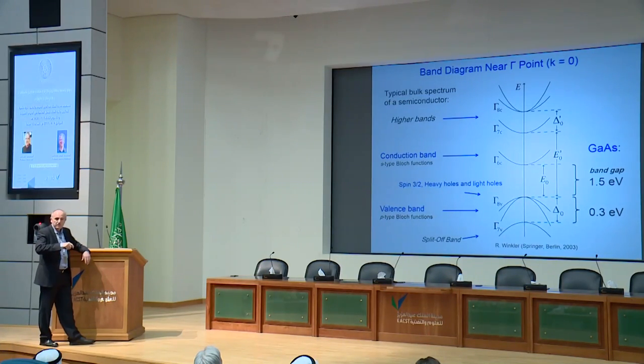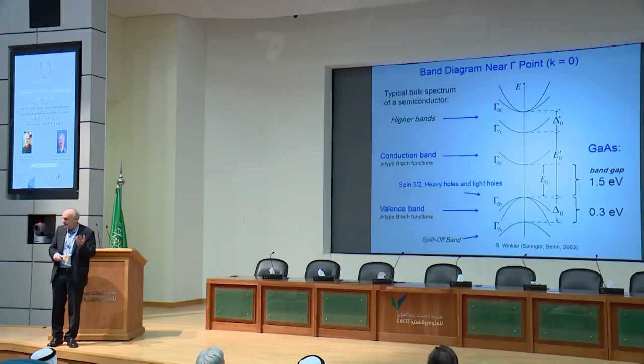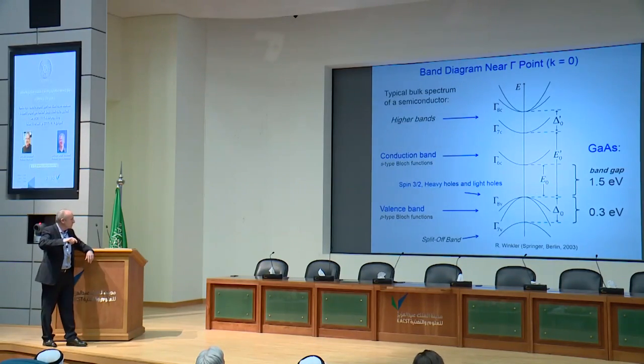Lawrence already showed actually a picture of that, the band structure picture. Typically, we like to be here in the conduction band, where the curvature of the band is positive, we have a positive mass. But the valence band is also very interesting. It has some issues because we have here degeneracy of several levels, and then it's not so easy to define a spin. And the contribution from the underlying lattice, from the atoms, is that here we have mostly P-wave contributions, where here we have S-wave.